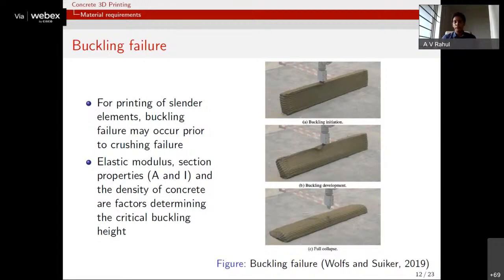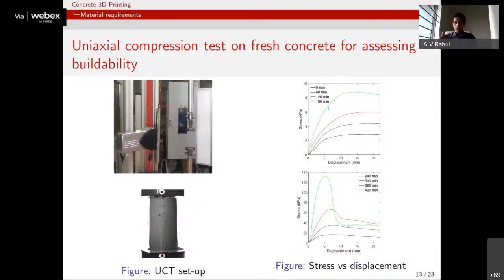Now, here again, buckling failure will also depend on the section properties or the moment of inertia. For example, if you have a printed element with a high moment of inertia, that will provide a higher resistance to buckling failure. The cross-sectional area and the density of concrete will also influence the resistance to buckling failure. Having understood that the elastic modulus as well as the compressive strength are both parameters influencing plastic and buckling type failure in fresh concrete,